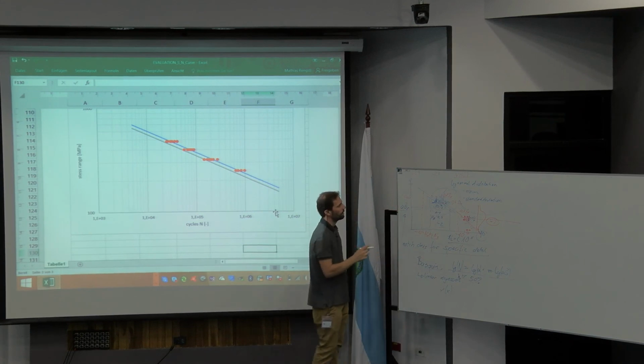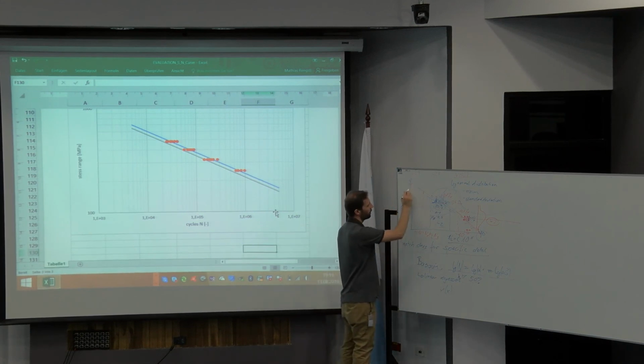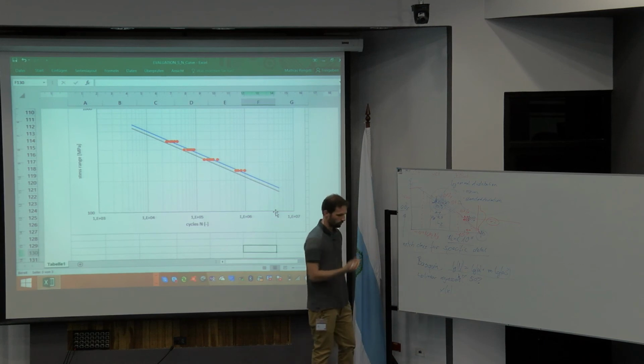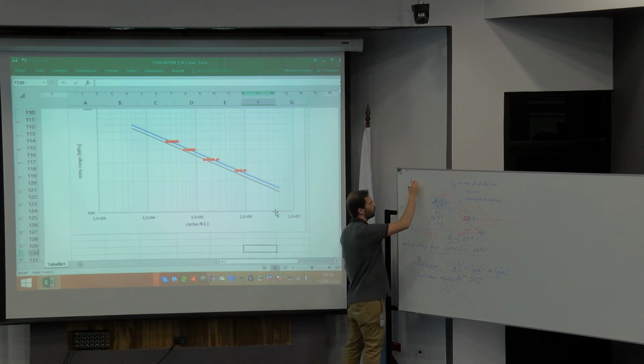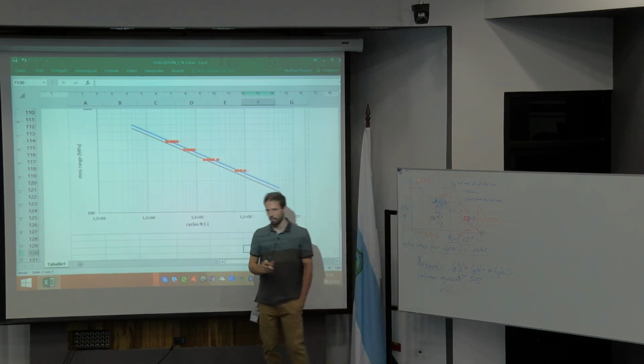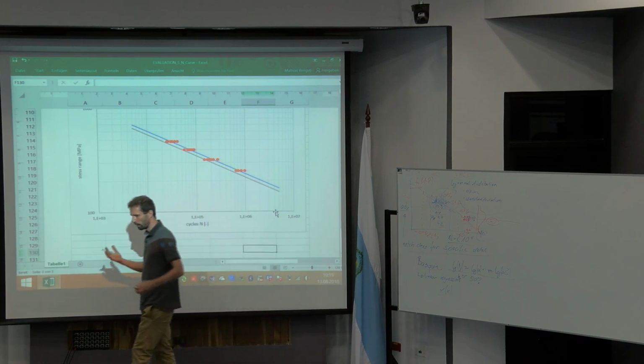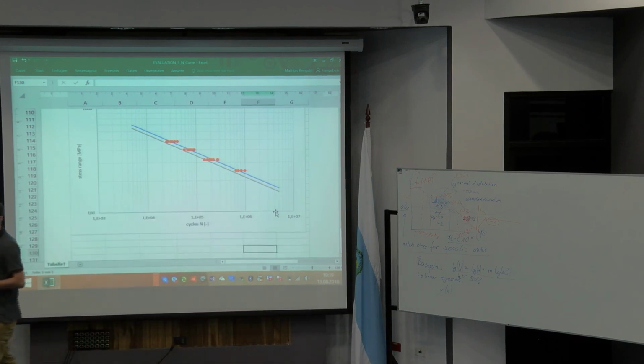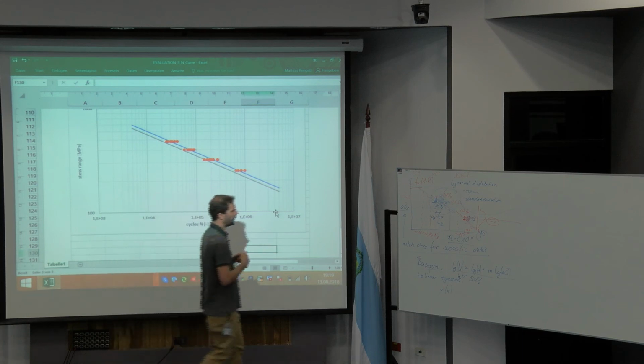And for the LCF, you have here usually a plateau, which is defined by Fu times 1 minus R, so which is given by the ultimate tension strength of the material, and of course due to the definition of the stress range.